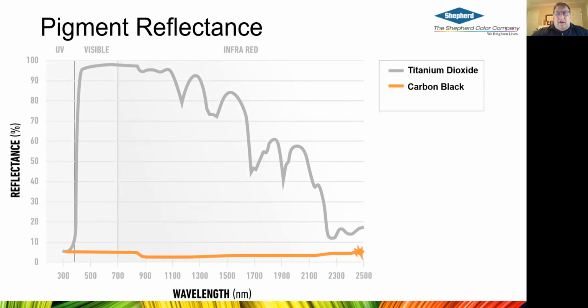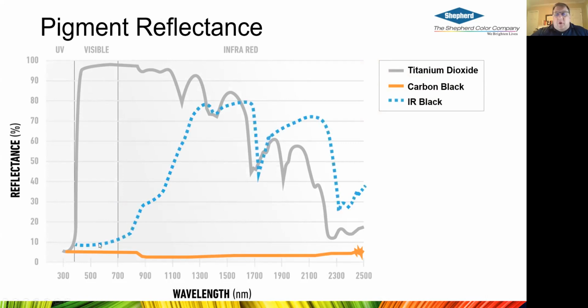The science behind the IR reflecting pigments is that they absorb in the visible wavelengths of light so that they're dark, aesthetically pleasing colors. But once they get into the invisible infrared wavelengths of light that our eyes can't perceive, they start to reflect and scatter that light back out of the film and plastics. So what you have is the aesthetically pleasing dark colors, but you have the reflectivity of the more bland white pigmentation. Whereas the white pigment will have around 80% reflectance for TiO2 and 5% reflectance for carbon blacks, these infrared reflecting blacks will have a TSR between 25 and 30%.